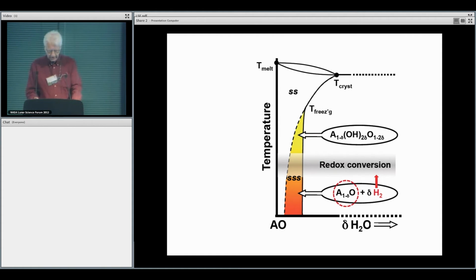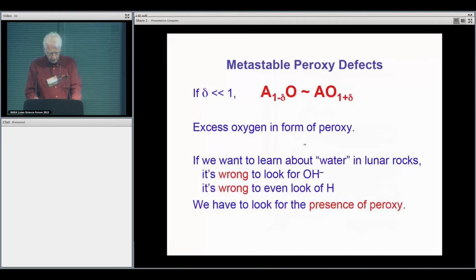The next slide shows how you can approximate this. You can say if delta is really small, you can rewrite this approximately as a mineral with excess oxygen. Now this is a metastable state. It forms only in a temperature regime where thermodynamic equilibrium can no longer be achieved, but this is a composition that we would have to take into account.